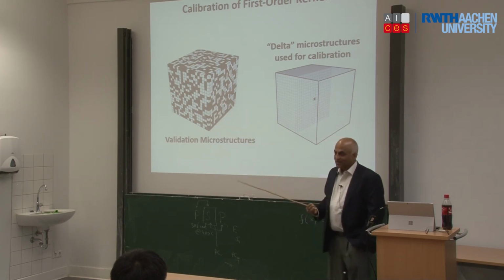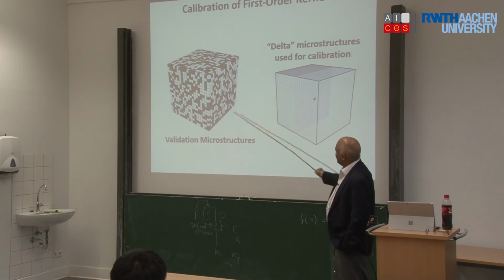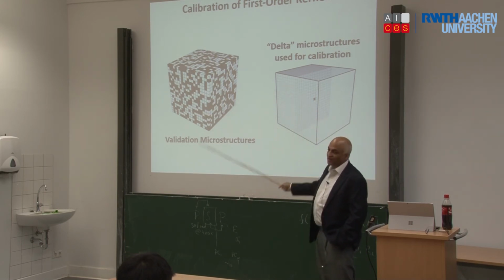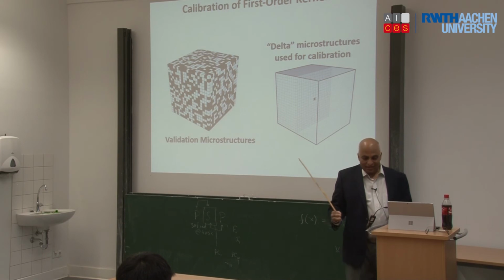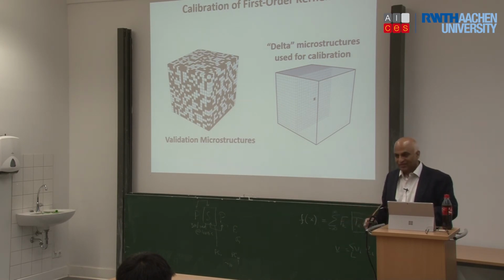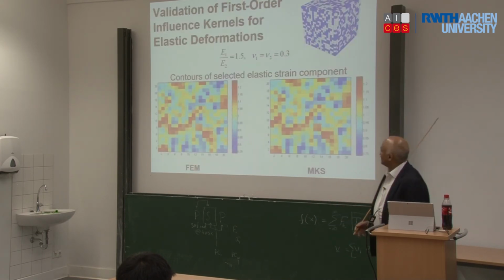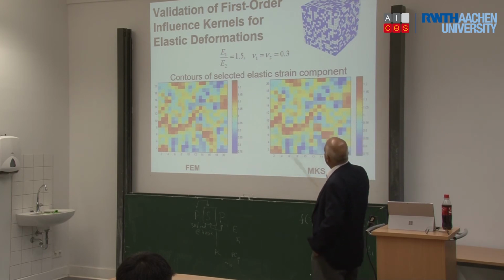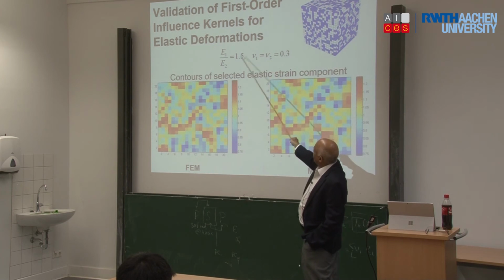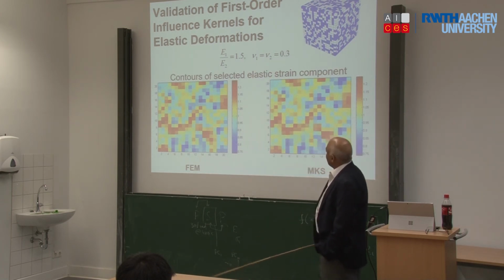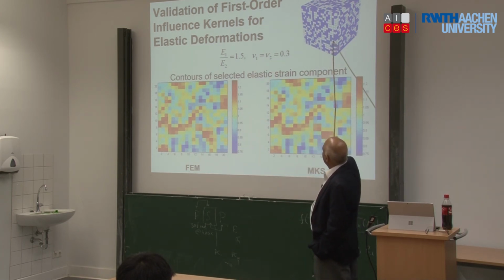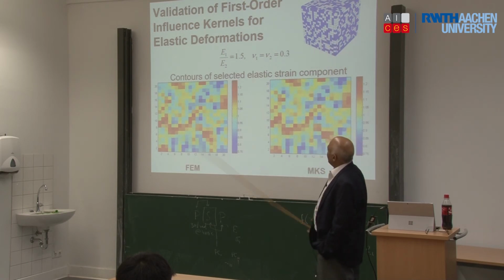Right? And the reason I'm saying that is that this is not an interpolation of this. Now I'm able to extrapolate, and I cannot do that until I have some physics in there. And this is the proof that it works. This is 2-phase materials, so this is an actual microstructure. The contrast is 50%. So, one of them is 50% stiffer than the other, and this is a midsection of both.